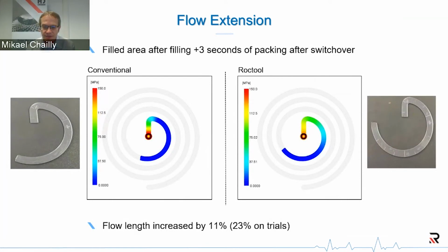Here you have the first flow extension measurement. So we have the correlation of the filling, the flow front position, from conventional conditions and Roctool conditions, after this dynamic filling and 3 seconds of packing, or static pressure controlled filling after switchover. Typically from the simulation, we could see an increase with this pressure limit at 1,500 bars of about 11% in Roctool conditions. And now you can see on the pictures the real samples, and basically we have gone up to 23% flow extension doing the real thing.